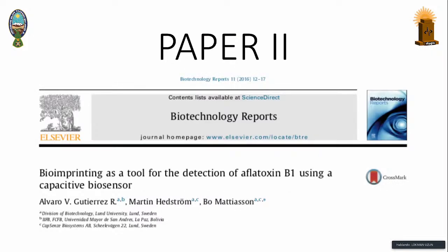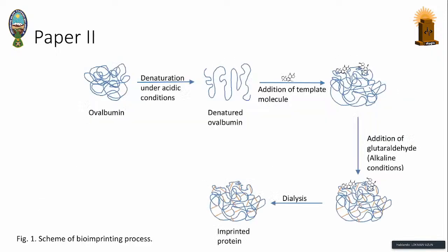In the second paper, the direction changed, because the self-assembled monolayer has some disadvantages. Moreover, antibodies have disadvantages according to cost and the immobilization process, so another approach, a bioimprinting approach, was applied in this study. Here, ovalbumin was used as a bioimprinting substrate, firstly denatured, then in the presence of aflatoxin cross-linking produced bioimprinted proteins. It has selective recognition cavities in itself.